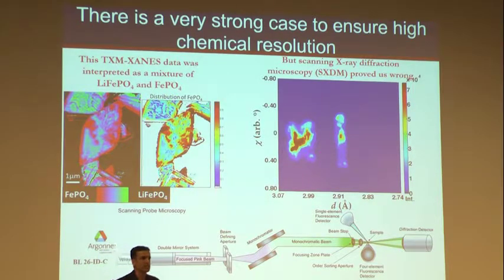For a variety of reasons, we wanted to get similar insight, but now using diffraction instead of spectroscopy. Diffraction has the added component that you can look at strain, and when you're worrying about mechanical events, measuring strain is very, very useful. This was done at the nanoprobe here at Argonne, beamline 26, where we have a small beam that is being scanned on the sample, and a detector that detects the diffracted intensity. Then we rock the particle around a diffraction peak to see where that diffraction peak appeared in 2 theta.